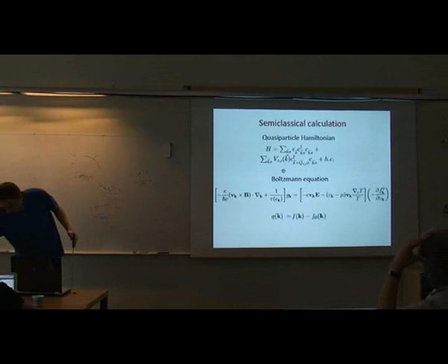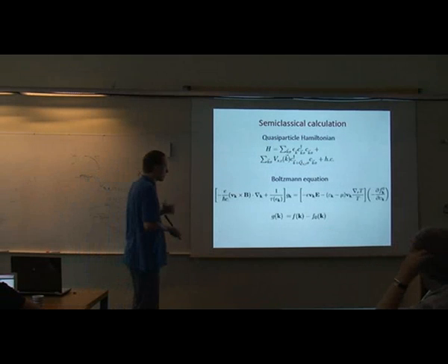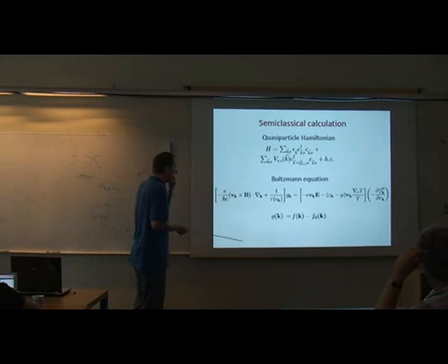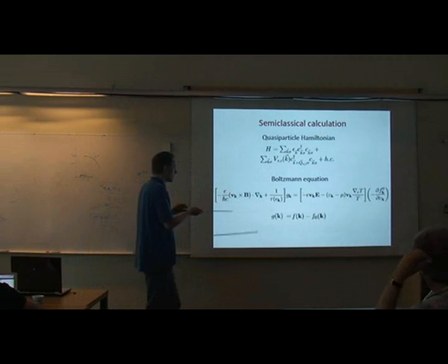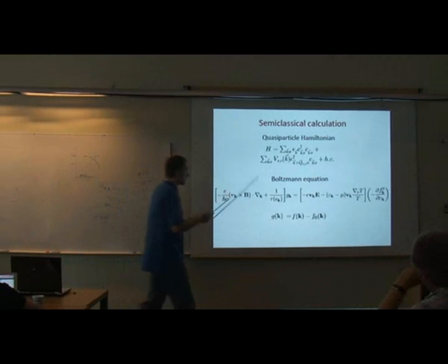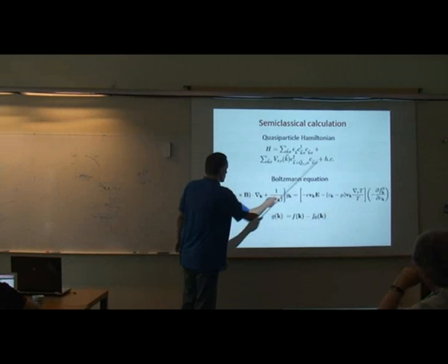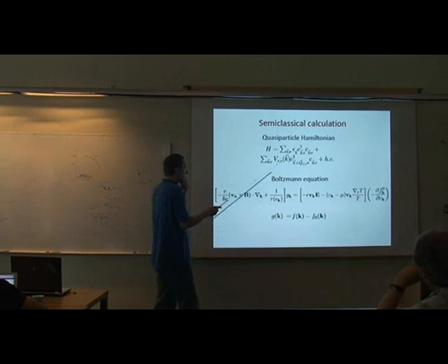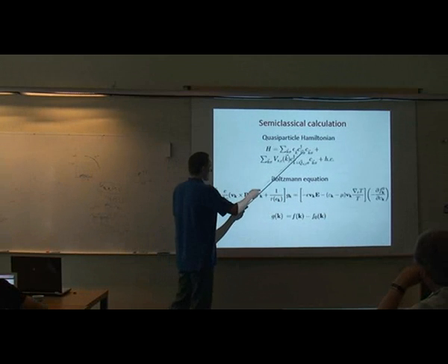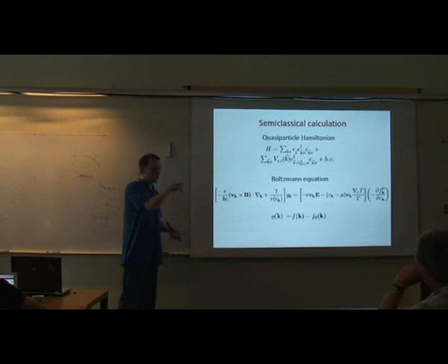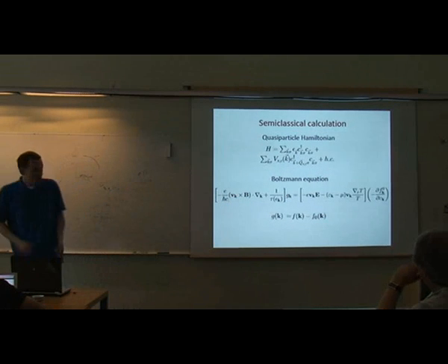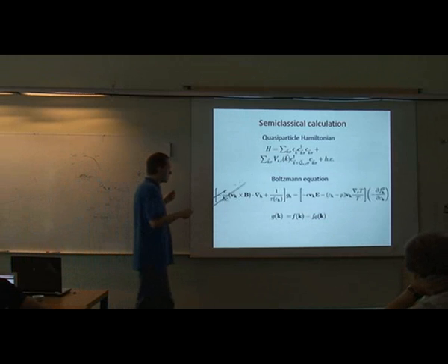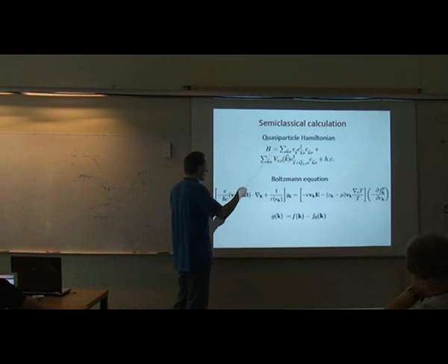That's how I'm going to calculate this signal. The system I assume now covers the basic aspects of stripe order. That's the scattering potentials, which scatter the quasi-particles. And on top of that, I just add the usual normal state dispersion on the square lattice, hopping with t prime, t double prime. And this captures the aspects of the broken translational symmetry.